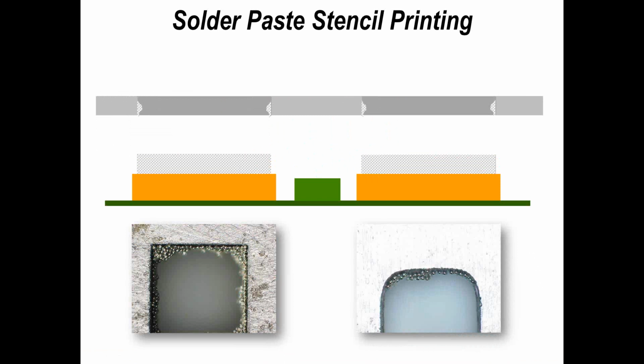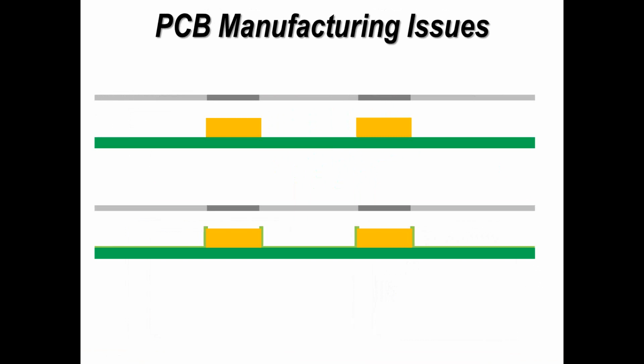With most of the standard components we use in the industry, slight variability on the volume of paste is not a major issue. And it really is the ultra small packages and the ultra fine pitch where small variability may not allow us to form a solder joint. We need to also consider the printed circuit board, and this is particularly true, again, when we're going to finer and finer and smaller parts. So in this particular example, I'm showing you some small, possibly passive parts being printed.